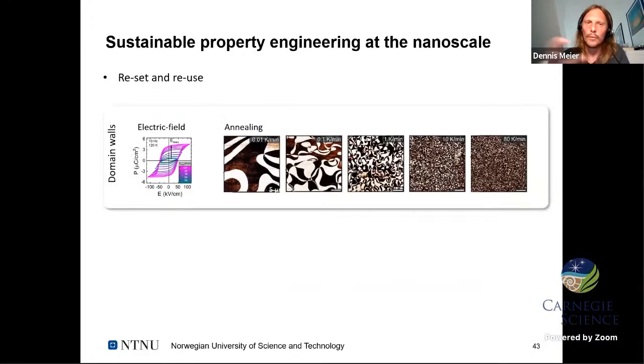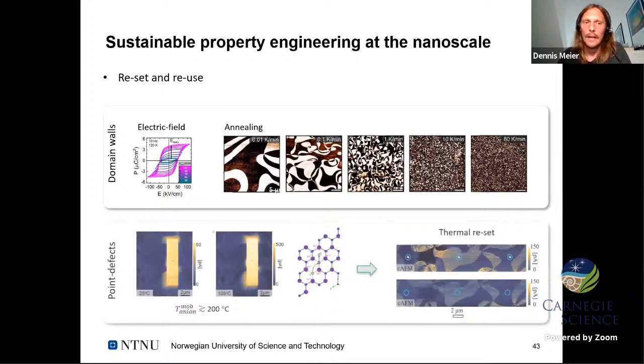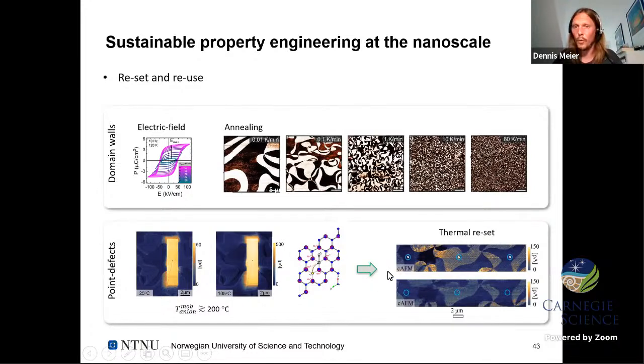And you can also set and reset the structures just by annealing and electrical fields. You can play with the domain walls, their number, and if they are in your devices, you can change that. We have the point defects, the very same. You can anneal them and even reset the structures, because at some point your oxygen becomes mobile, and as we've shown here with the thermal annealing, you can reset the structures and get rid of the conducting features.